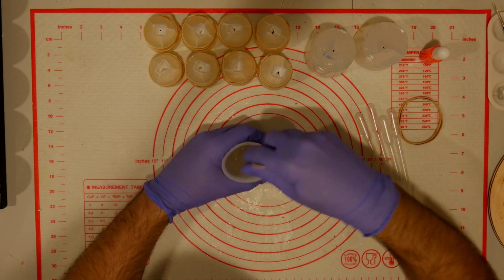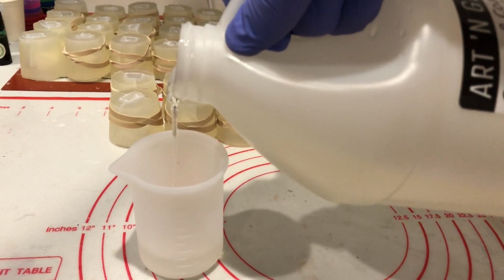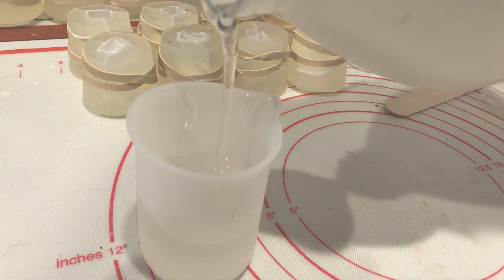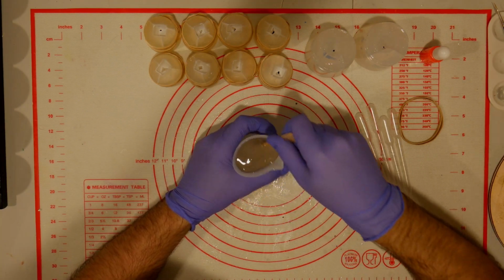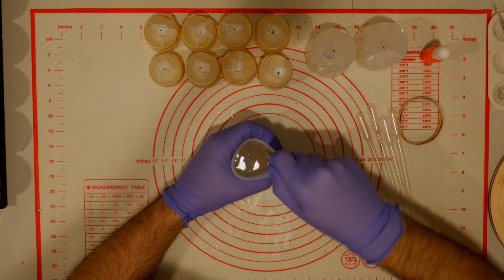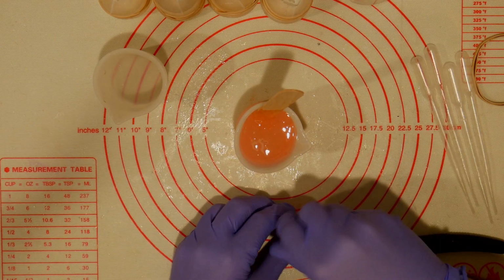Art 'N Glow resin, like many other epoxy resins, is 1A to 1B by volume, so it's 40 milliliters of part A and 40 milliliters of part B. Stirring vigorously on all 3 axes, as you've heard me say, just like with the silicone, it's time to add the ink. I use this special new resin inclusion resin dye, and I add about 6 drops, and it doesn't really look the best.